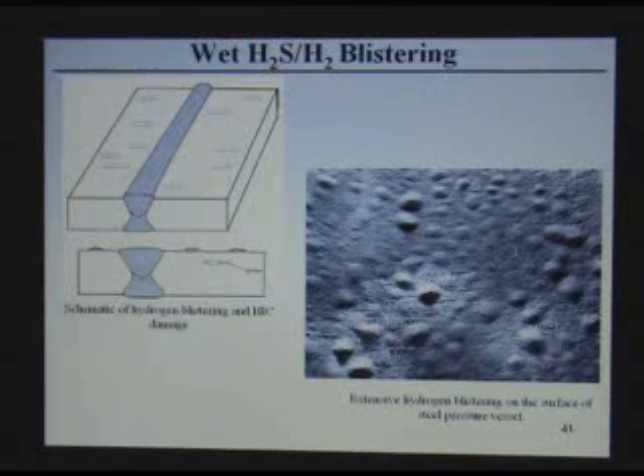The types of wet H2S cracking. The first one is blistering. You can have the hydrogen from corrosion diffuse into metal and accumulate and cause blistering of the surface. So this is one area of accumulation of hydrogen, another area of accumulation of hydrogen, and it interconnects this way, and they call it hydrogen-induced cracking. This one is blistering. You can see the blisters here, and it doesn't show cracking, but only blistering.